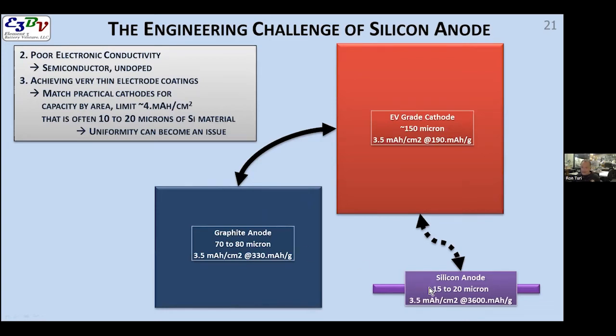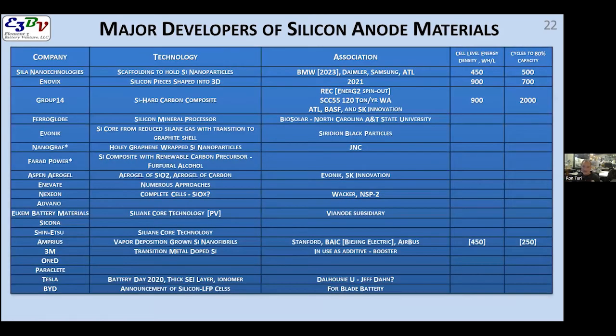And if you move over to silicon, you can reduce that to 15 to 20. That's a reduction of 50 or so microns in a cell that's about 150 microns total when you've got the anode, cathode, separator, and current collectors. That means you can reduce the thickness of your electrode to 2/3 reciprocal, so you've just increased the energy density by 50%. And this is the big hook and why people talk about silicon anode replacing graphitic anodes. When you have silicon anode, you can go to 900 watt hours per kilogram instead of the 600 when the cells are fresh. However, there are challenges, and we can certainly get into that.